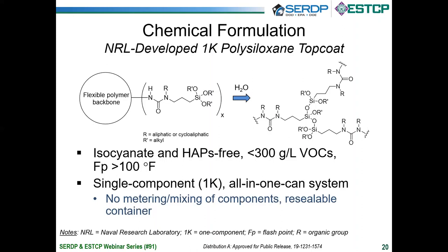Okay, so the first top coat technology that I'll discuss is a Naval Research Laboratory developed single component polysiloxane top coat. This top coat is based on alkoxysilane functional substituted urea polymers. So it's a hybrid polymer that contains organic and inorganic components. The way that this coating crosslinks is that these terminal alkoxysilane groups react with moisture, they hydrolyze, and then the silanol groups condense to form a sol gel or somewhat of a polysiloxane linkage, as is shown on the right